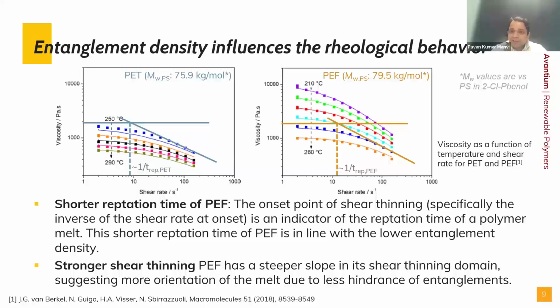And how is it calculated? There is a slope calculated on the rheology curves, and if we compare the slope between PET and PEF at any specific viscosity, then we see at what shear rate this viscosity is reached, and the inverse of this shear rate is actually the reptation time. So in case of PEF, the shear rate is higher at the same viscosity level, and the inverse means if the shear rate is higher, then the reptation time is lower. And this is actually what we want to understand.